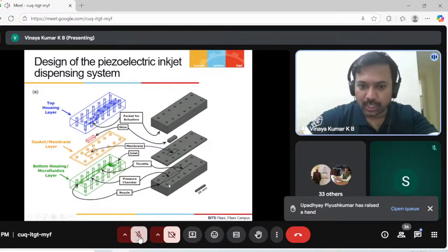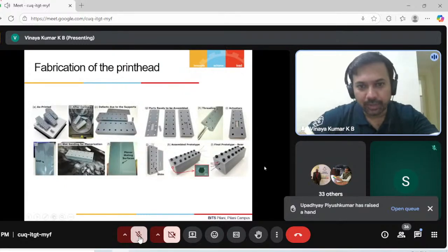We produce the microchannels, the pressure chambers, and the nozzle, and then we were able to assemble it in such a way that it can be used to print functional inks which have different viscosity and different surface tension. This is the complete fabrication process. We 3D printed the membrane.